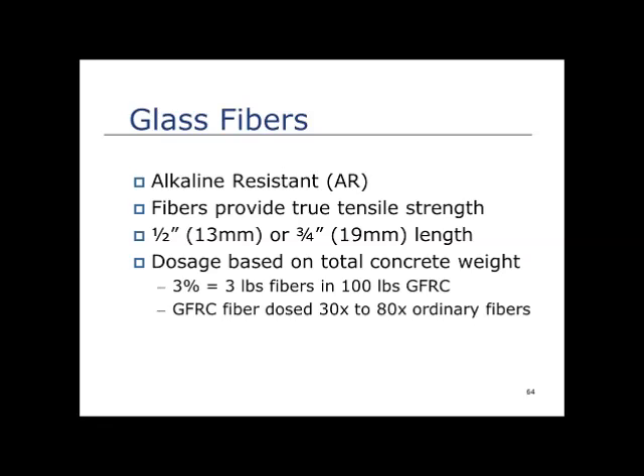It's 3 pounds of fibers added to 97 pounds of essentially mix coat to create 100 pounds of backer. So a 3% fiber dose means 100 pounds of backer that has 3 pounds of fibers in it. And to give you an idea how much fiber that is, ordinary concrete that might use a stealth fiber they might put in a driveway or floor or patio, that's 1 to 4 pounds per cubic yard, or 1 to 4 pounds per 4,000 pounds of concrete. So we're using 30 to 80 times as much fiber, or even maybe 100 times more. And that's what it takes to make it strong.